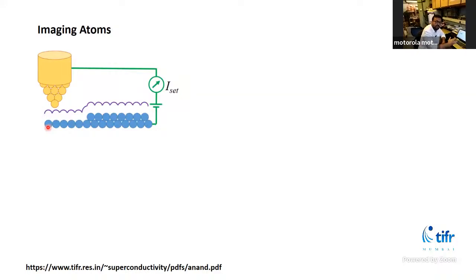As you move your tip, note that an atom has an electronic cloud over it. So tunneling is higher at the apex of your atom, and when you go between your atoms, the electron density will be lower there. So as you move your tip, the current will fluctuate, going from the center of an atom to between atoms, and again the center of atoms, etc. This will lead to a correction in the piezo tube that will then move across the sample, basically tracing out how atoms are placed. And if a step comes, it will go over the step, keeping a fixed current value. So measuring this voltage will give you a direct correlation with how atoms are arranged.